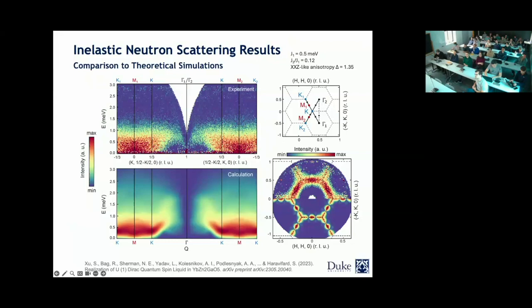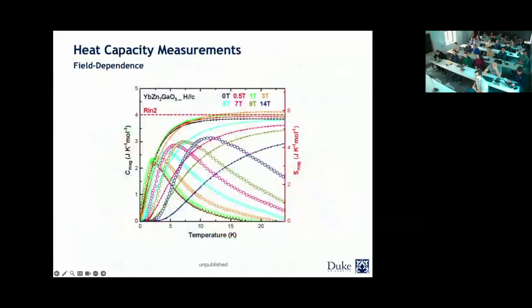So here you're looking at, again, the simulations versus the experiment. The reason that you see them in blobs is that this was done by DMRG, and so there's a finite size effect that's making the resolution not perfect, okay? So that's a good indication that so far there's sort of an agreement between the two, but of course there's still more that needs to be done to definitively pinpoint whether it is truly the Dirac quantum spin liquid.